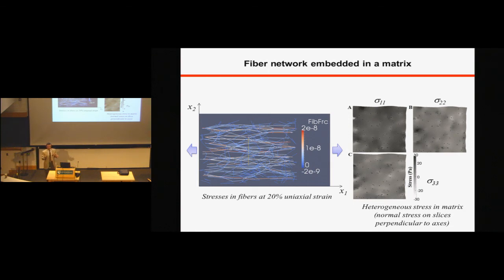If you forget about the network and you deform just the matrix, it is a homogeneous material. So deformation is going to be affine, which means everywhere you look, you are going to see the global strain imposed. Now you put the network inside. The network doesn't want to deform affinely because it's a heterogeneous material. So this heterogeneity of the deformation of the network actually gets transmitted to the deformation of the matrix. In other words, the network is going to pull on the matrix in various ways, trying to break it. Okay? It turns out that you would expect failure to start in the matrix, not in the network.